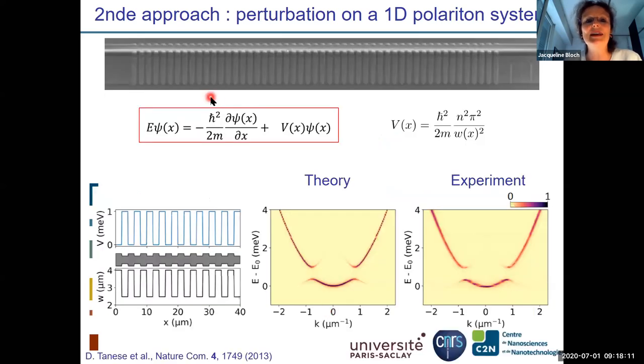And then I can show you here a wire which is periodically modulated. So you see that you have some regions which are smaller, so the confinement energy is larger, and you have regions which are wider so that the confinement energy is smaller. So at the end, you have free propagating polaritons perturbed by a periodic potential, whose height you can control by changing this modulation, and you can control also the periodicity. And so what you expect is that you are going to create new Brillouin zones and form mini bands with mini gaps. And this is exactly what you see.